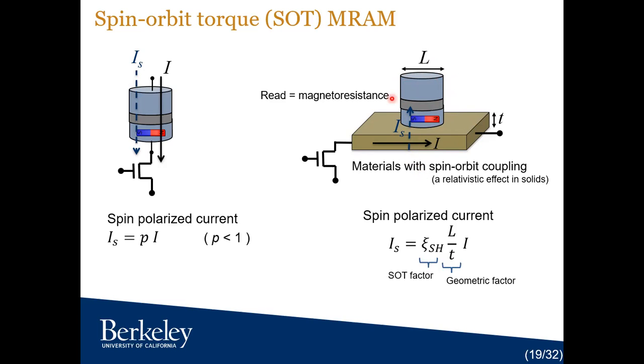So there are a few benefits. In STT, spin current is proportional to the charge current, and there is an efficiency factor that's less than 1. But now your charge current and spin current are in two different directions. That's why you pick up a geometric factor, which can be much greater than 1. And also there is this efficiency factor, which is supposed to be the property of this material. This can be greater than 1 as well. So overall, this coefficient can be much greater than 1. So we can create large spin current for a given charge current.